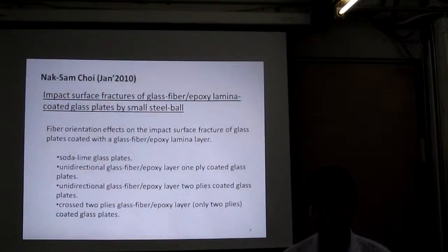Impact surface fracture of glass fiber epoxy laminate coated glass plate by small ball. One study of fiber orientation effect on impact surface fracture of glass plate coated with a glass fiber epoxy laminate layer was investigated using a small diameter steel ball impact experiment. Four kinds of materials were used in this study: 1, soda lime glass plate; 2, unidirectional glass fiber epoxy layer 1 ply coated glass plate; 3, unidirectional glass fiber epoxy layer 2 ply coated glass plate; and 4, cross 2 ply glass fiber epoxy layer coated glass plate.